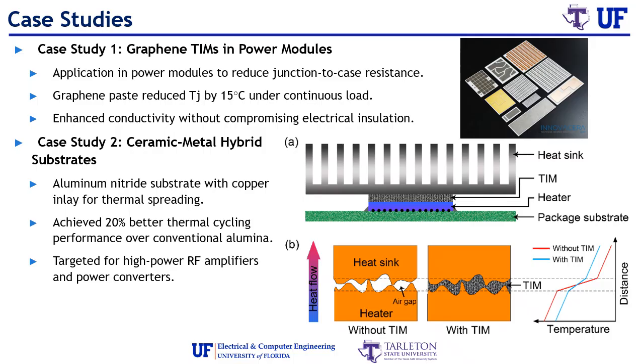Now, in case study 2, we go through a ceramic metal hybrid substrate. Over here, it uses an aluminum nitride substrate with a copper inlay, which can also improve the thermal cycling by 20% over conventional alumina. This is targeted at high-power RF amplifiers and power converters. As you can see in picture B, the heat sink and heater temperatures fluctuate with different TIMs.